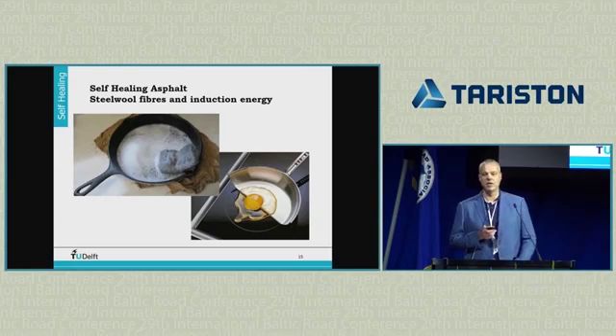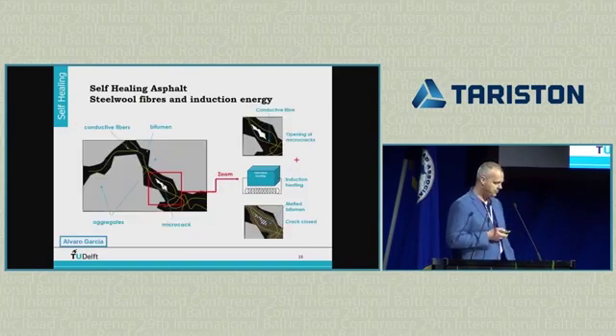This will melt the bitumen, it will close the small cracks, and your stones stay where they are. Of course, you have to do this before the stones come off, because you cannot put the stones back. So you have to do this treatment just before the stones are driven out of your road. So if you have micro cracks in your system.